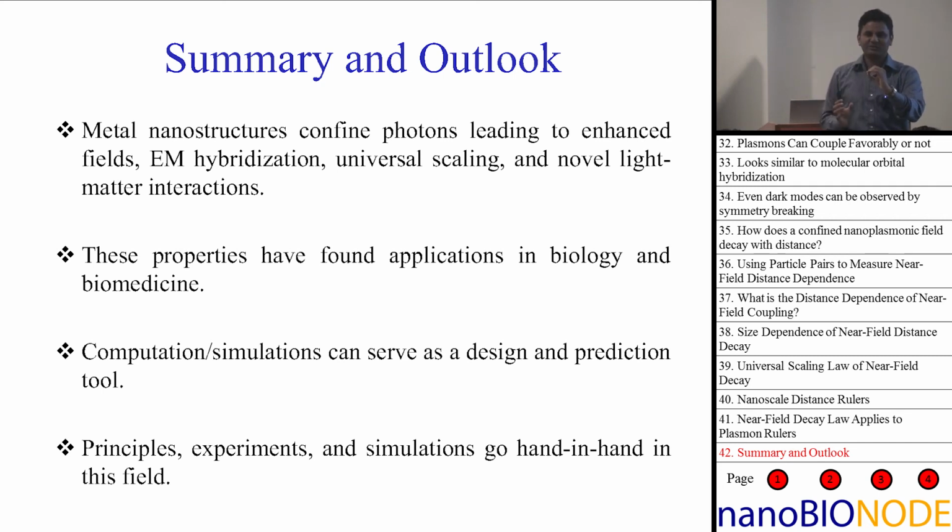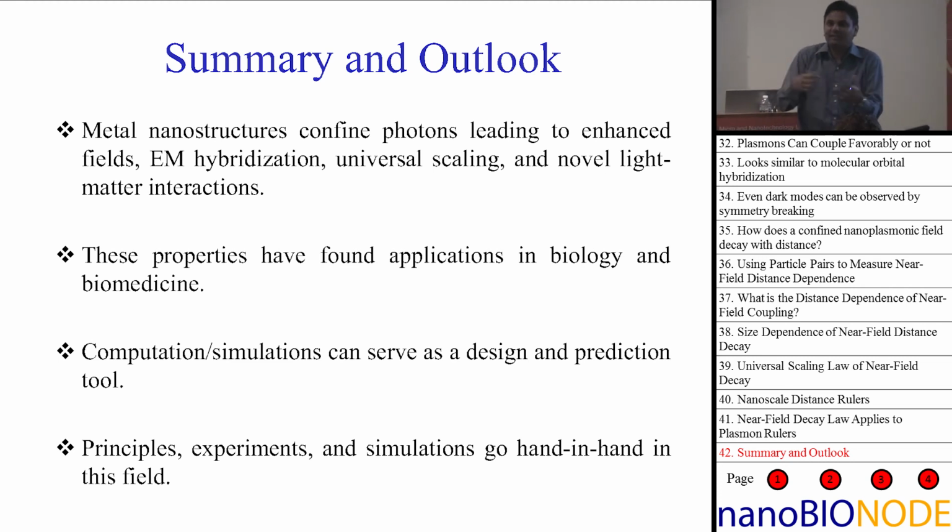In three dimensions, instead of the separation divided by the size, what matters is the volume fraction. That's the three-dimensional version of the same quantity. S cubed divided by D cubed takes the form of a volume fraction. So as you add back more and more particles, you increase your volume fraction, and your particles are closer on average in three dimensions, and so you see a larger redshift because of the stronger coupling between these particles.